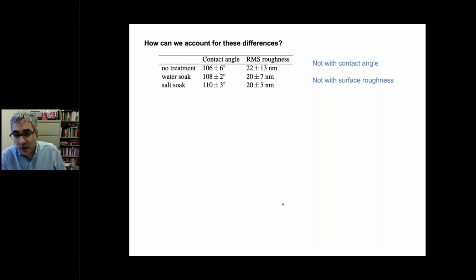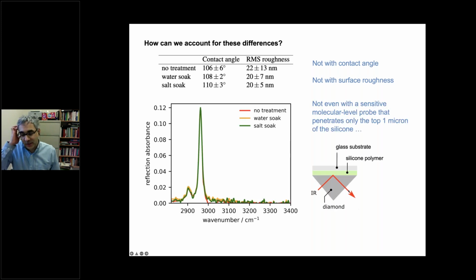So the other thing which is often discussed is that the roughness of the surface changes on a micro scale. But here you can see that even with a nanometer probe of the surface roughness, there's really no change in the surface becoming more or less corrugated as a result of environmental exposure. So this can't account for it either. So then what we did is we decided to go to an optical probe, which could give us a micron level description, looking at the top 1 micron, which is 1/1000th of a millimeter.